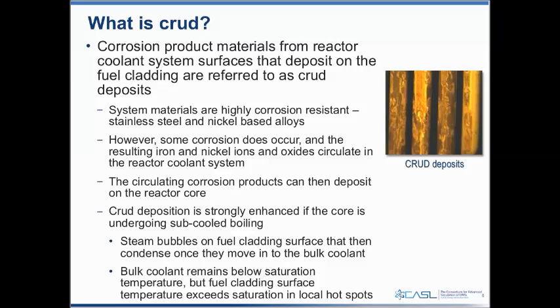The result is that pressurized water reactors operate below saturation temperatures for the bulk coolant. We never exceed saturation in normal operation. However, some of the cladding surfaces can be above saturation temperature during operation on the higher powered fuel assemblies and fuel rods. What that means is we then form steam bubbles on the fuel cladding surface. As soon as they move into the bulk coolant, they condense because the coolant is below saturation conditions.